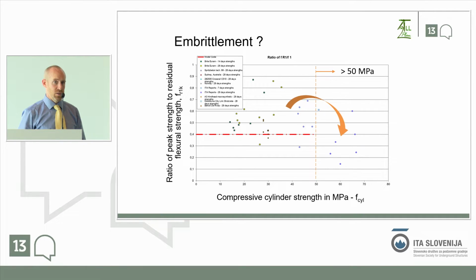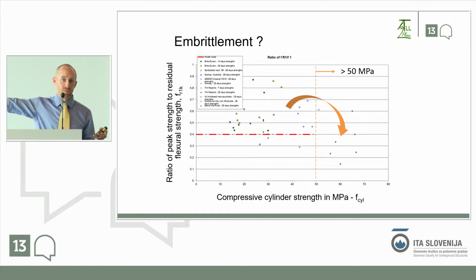That is not necessarily a good thing in the context of fibers. You're probably generally familiar that the idea is that you try and pull the fibers out. That gives you ductility. If the bond from the fiber to the matrix is too strong, it snaps, and we're back to a brittle material. And this can be a problem if there's sort of a mismatch, shall we say, between the fibers you have. You can see there's a bit of a trend towards a reduction in the residual flexural strength as the strength of the material increases. That's partly what's driven this tendency with steel fibers to have some of these sort of ultra-high strengths, because if you can harmonize the strength of the fiber with the strength of the mix, you resolve that problem.